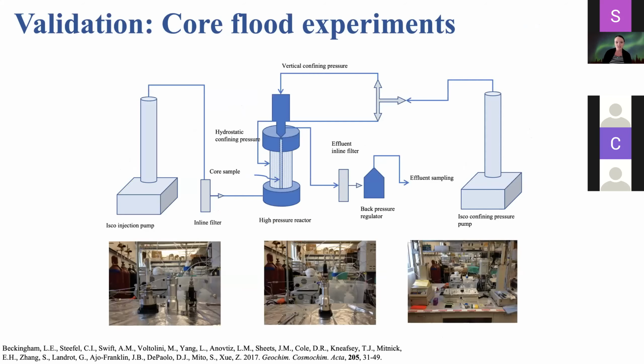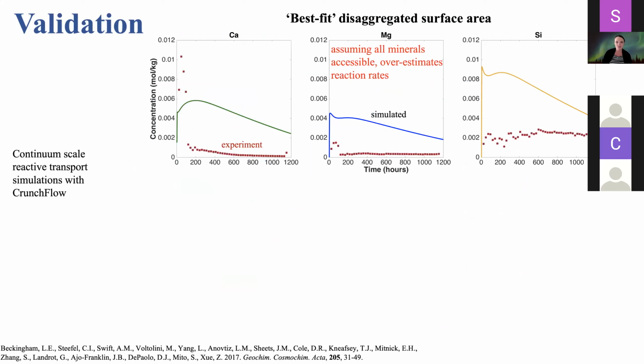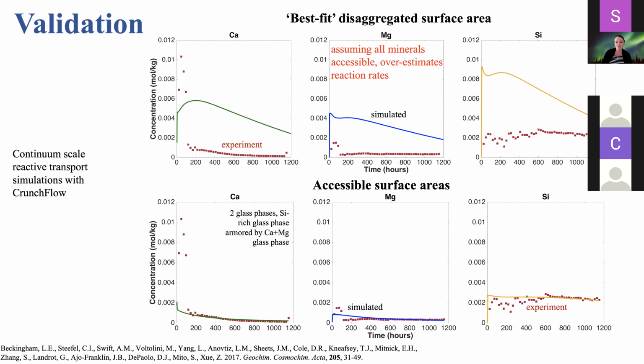We have validated this using a core flood experiment, mimicking conditions from the field site, and then used reactive transport simulations to evaluate the performance of these surface areas. Here you can see the experimental results from the core flood are in these red squares, and then this set of simulation results in the solid lines, where basically we're using a surface area that assumed all the mineral phases were accessible for reaction, and this really overestimated the reaction rates. Then if we use our image-obtained accessible surface area, we're able to effectively capture the reaction rates in our core flood experiment.